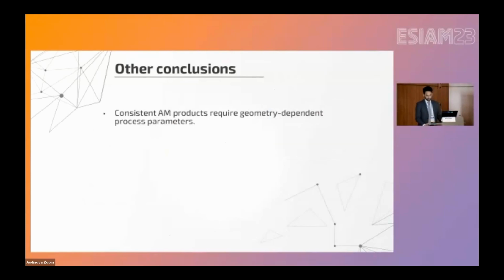Okay, let's draw two preliminary conclusions before I head on with the rest of the presentation. If we want consistent AM parts, we need variable process parameters. As long as you use constant process parameters, you have to expect the variation that you see in the microstructure. Besides that, we saw that the microstructure can very well be determined or linked to the thermal history during fabrication. So why, instead of having this unexpected gradient, don't we manipulate the process parameters to get the gradient of microstructure that we want.